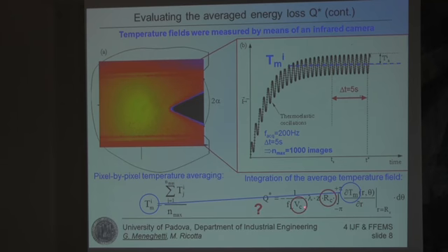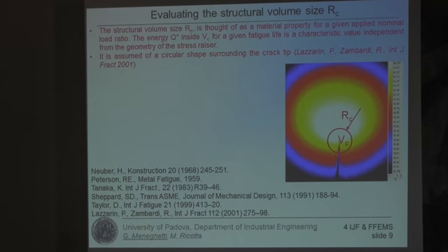Now, we have to define how big is the structural size surrounding the crack tip to complete our evaluation. We made some hypotheses. The first one is that the structural volume size RC is a material property for a given applied nominal load ratio, and the averaged energy inside such a volume for a given fatigue life is a characteristic value independent from the geometry of the stress riser. This is a very classical hypothesis which has been done in the past many times, but typically concerning notches evaluated at the fatigue limit. The second hypothesis is that the shape of the structural volume is a circle surrounding the crack tip.